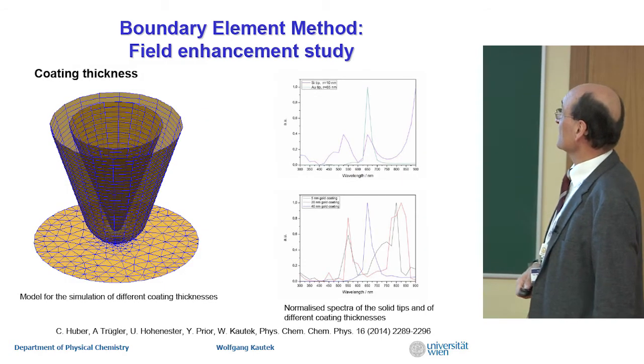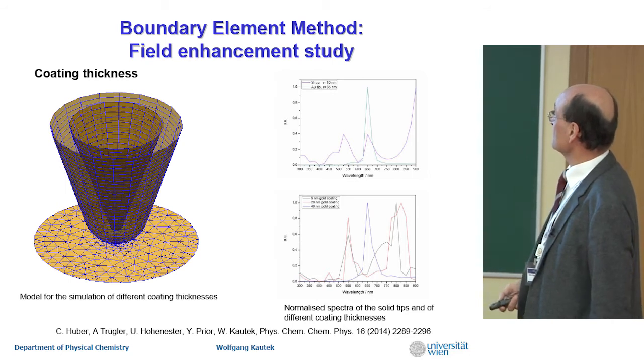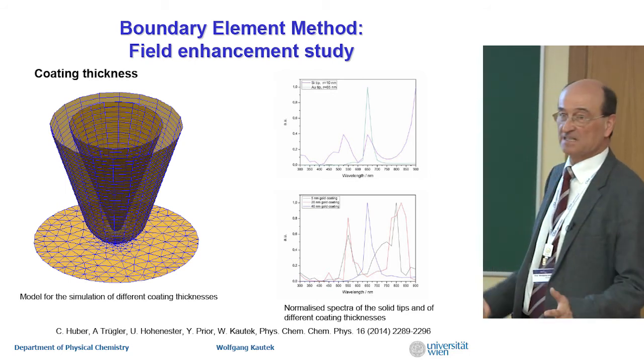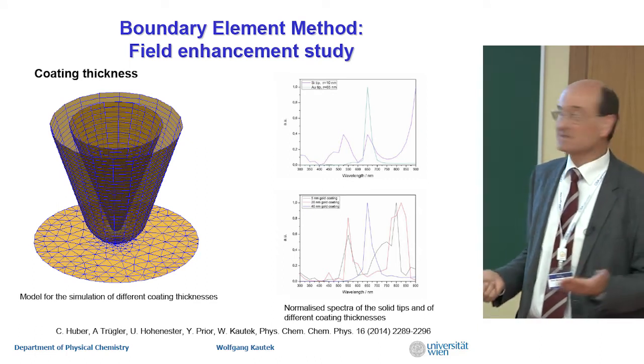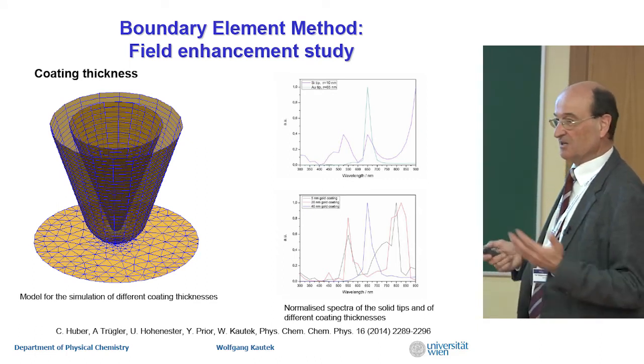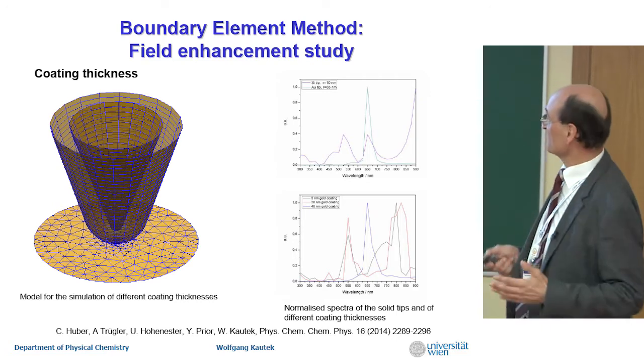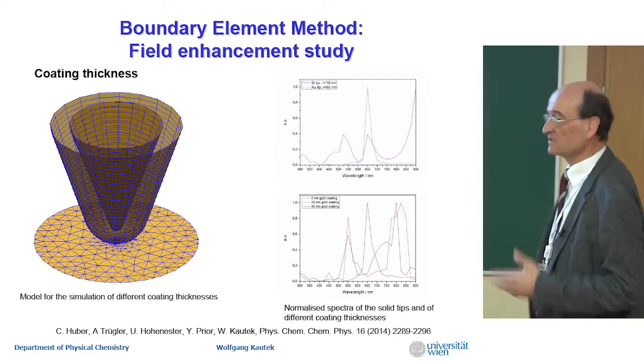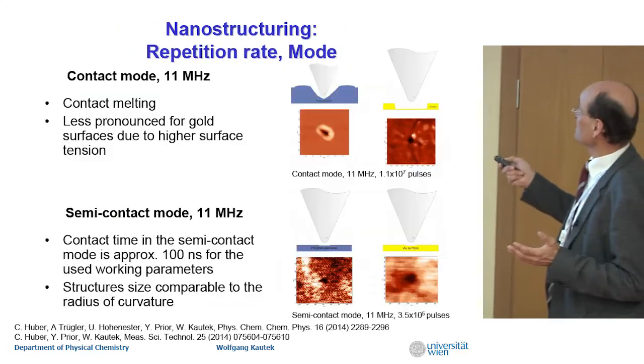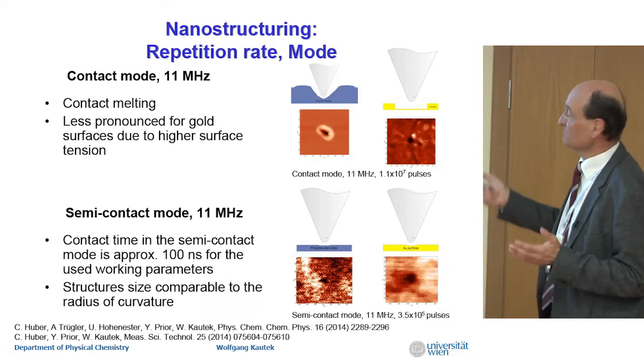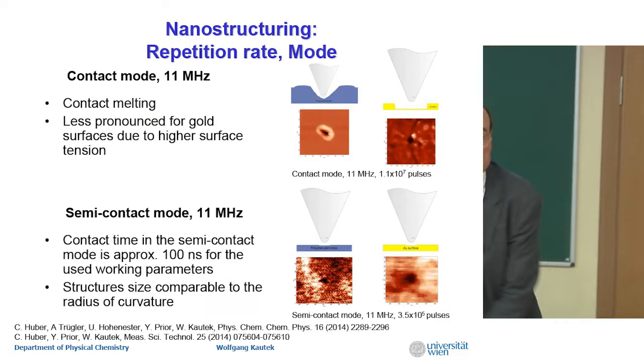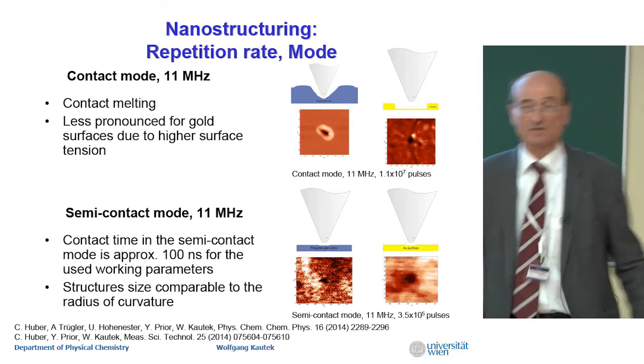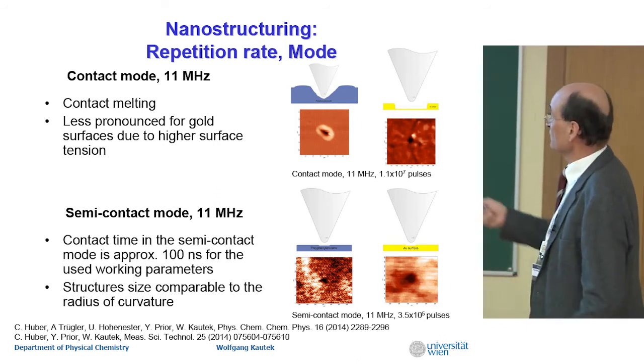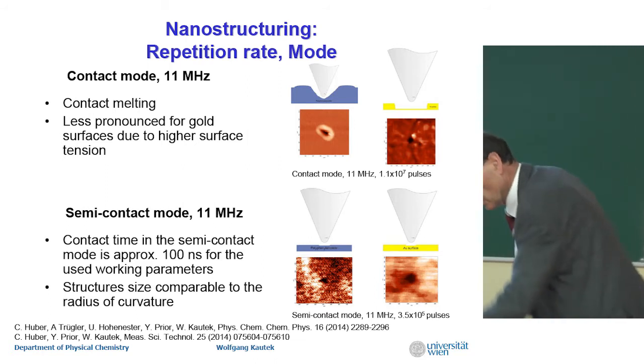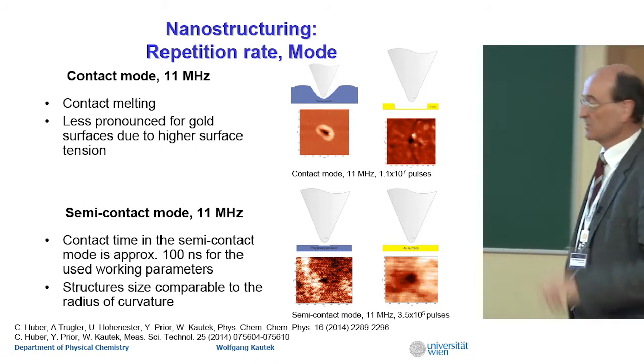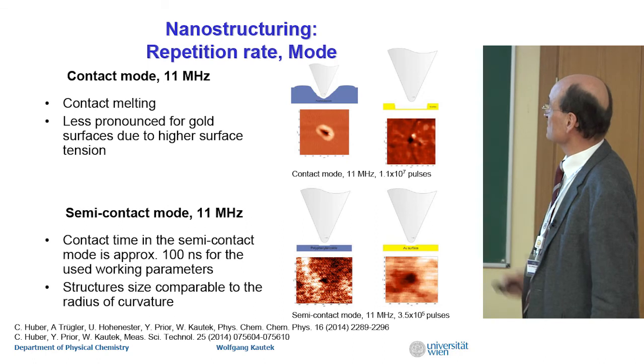Okay. Also, the coating thickness has an influence, and the wavelength has an influence, and we are not at optimum yet, so we would like to have an optical parametric amplifier, but we don't have the money at the moment, so it can be improved. But first results show that we get melting if we have a contact mode. The tip is hot, then you have melting of the surface. Clear, simple. If you have a semi-contact mode, then there is no heat dissipation and we get nanostructures at the surface.